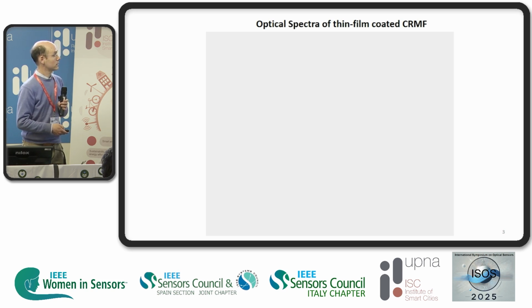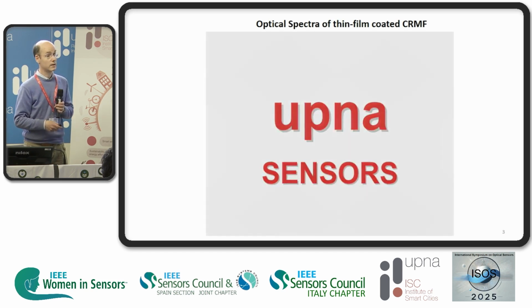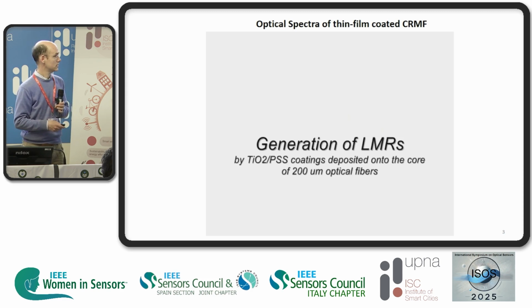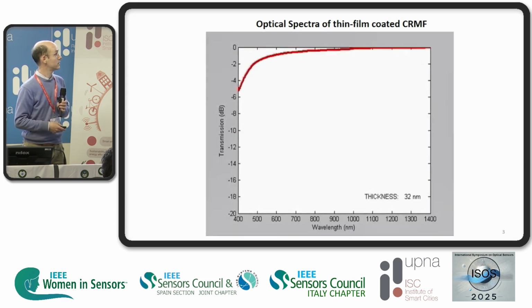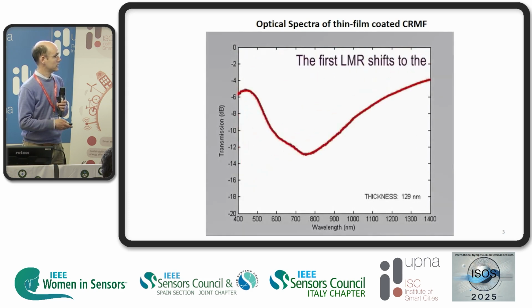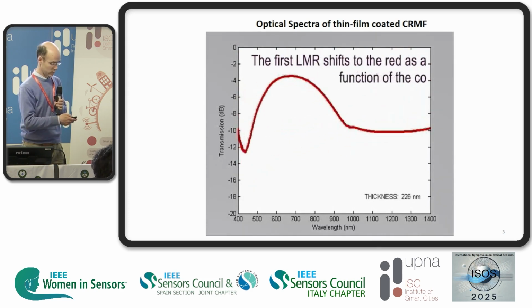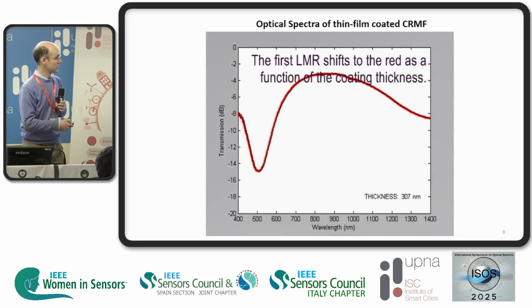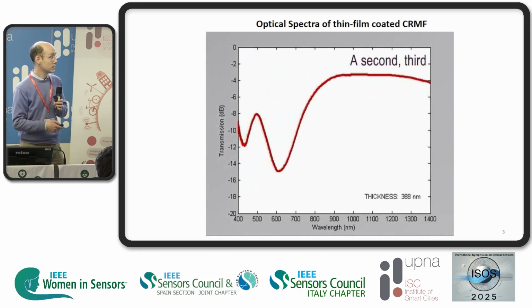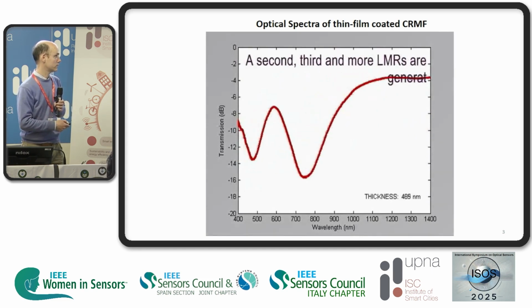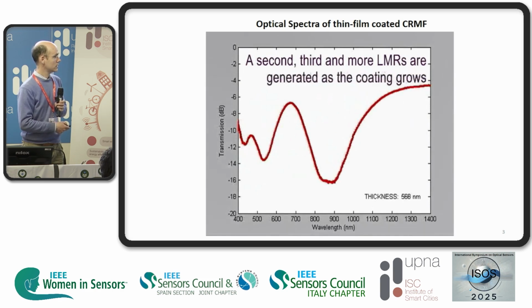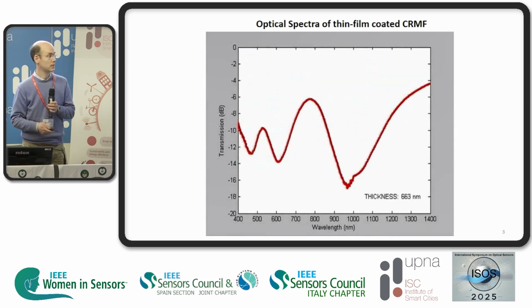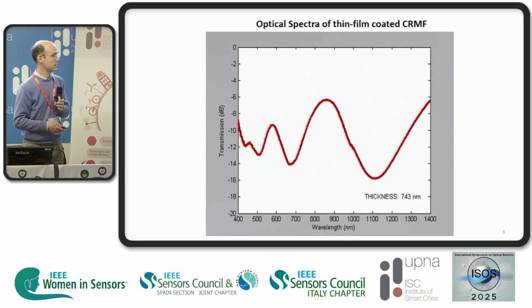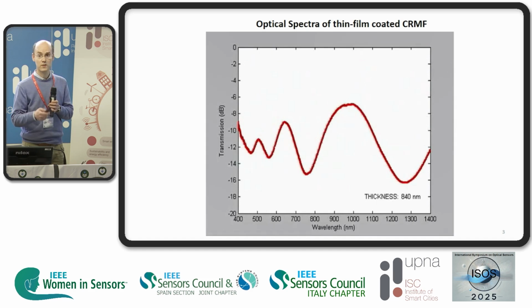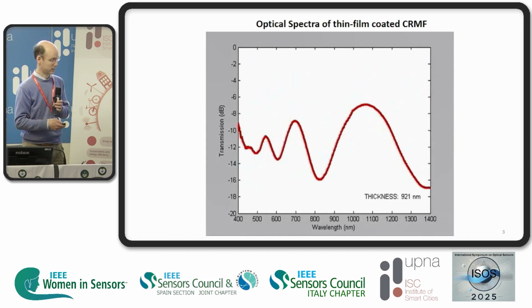Here is a video we developed at the beginning showing the wavelength shift of the resonances as we deposit a titanium thin film. During the first steps, as we deposit the thin film, we can see the first LMR, then the second one, and the wavelength shift of the resonances slows down. So as we increase the thickness, the wavelength shifts less. This is related to sensitivity, and we will explain later that sensitivity is related to the order of the LMR. It is better to use first order LMR.